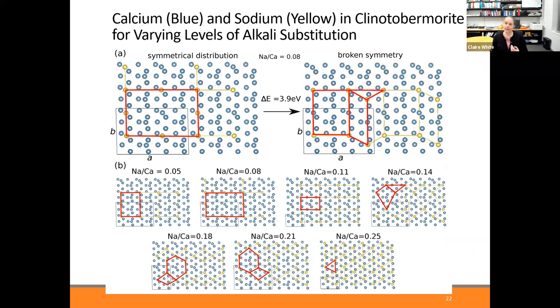So we can look at the formation energies of these structures with respect to the original clinotobermorite structure. I'm going to show that on the next slide, but what's shown on this page is that you can put the sodium atoms in different locations, so you can choose in the interlayer region essentially what substitution to do. That's what we had to do here. We did it manually. What we found is the location of substitution does matter.